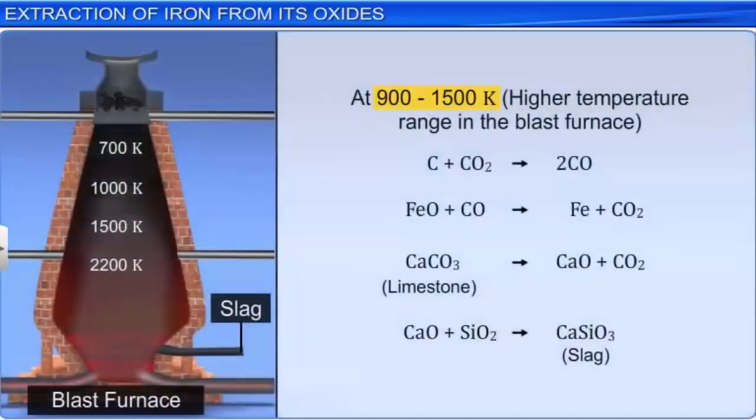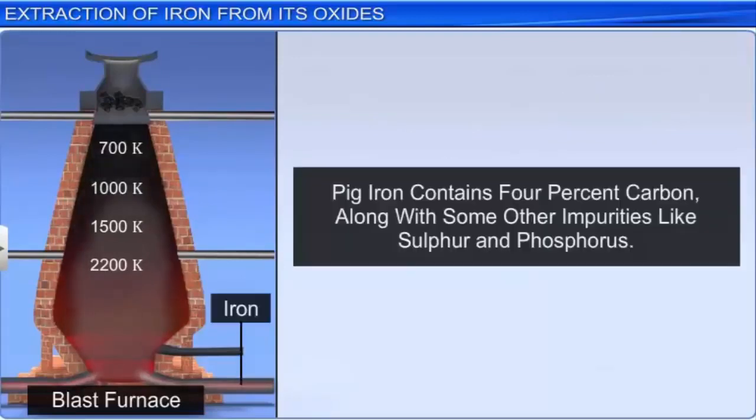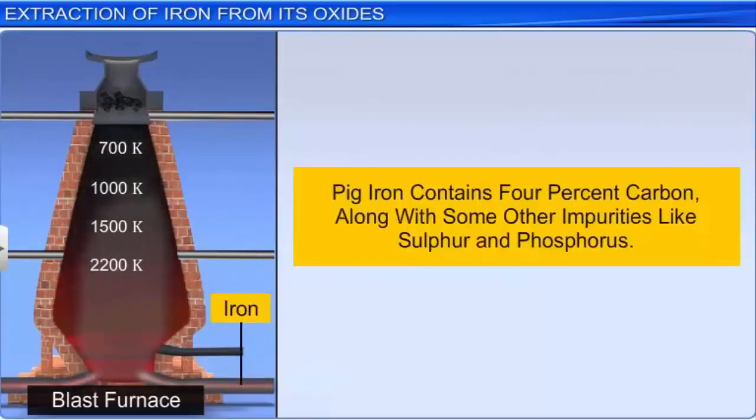In the temperature range of 900 to 1500 Kelvin, carbon monoxide reduces ferrous oxide to iron as shown here. Silica is an impurity. Limestone removes it in the form of molten slag, which is taken out from the bottom of the furnace. The molten iron obtained in this process contains 4% carbon, along with some other impurities like sulfur and phosphorus. It is called pig iron.